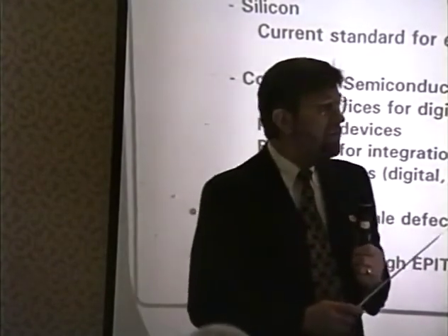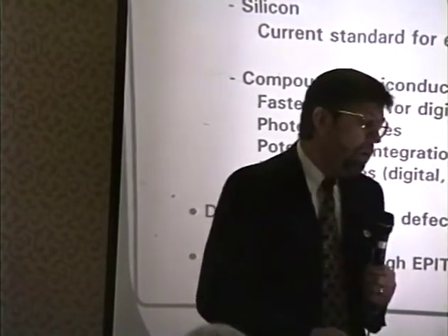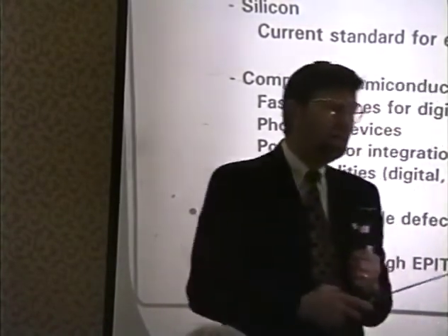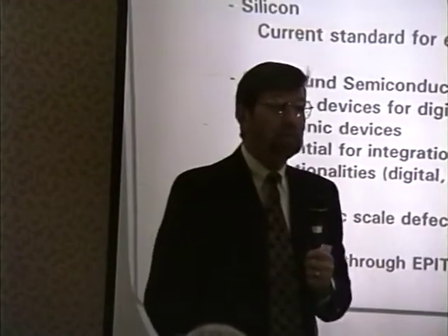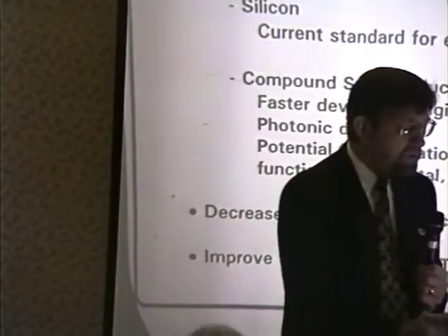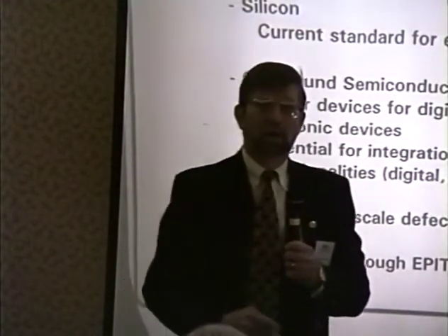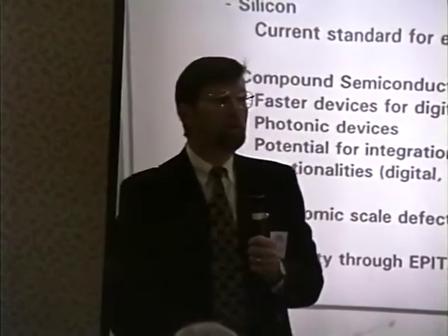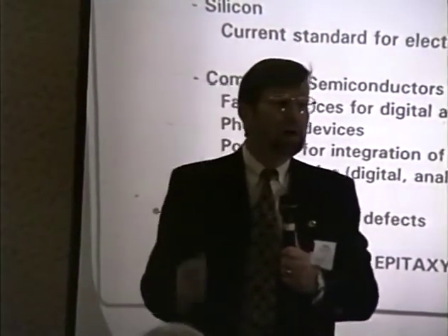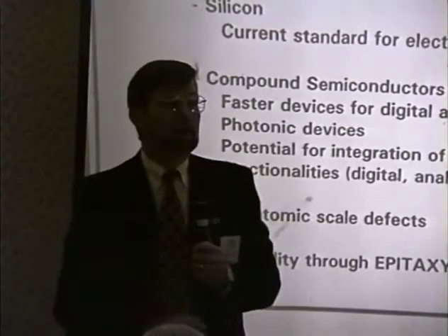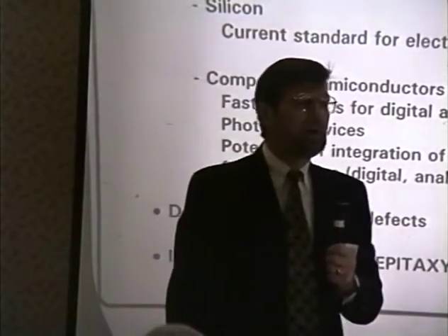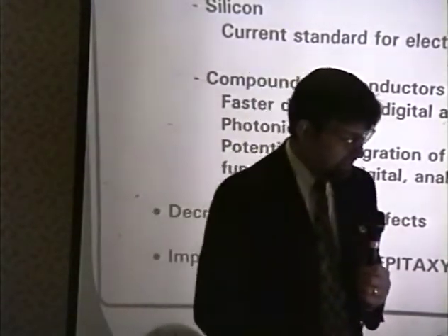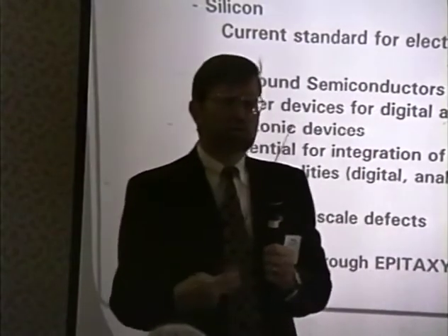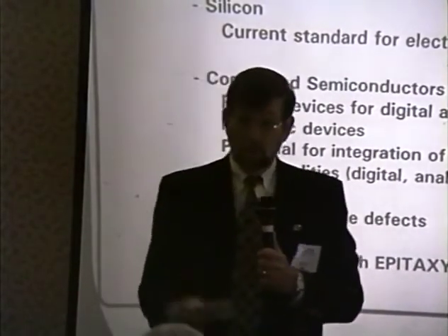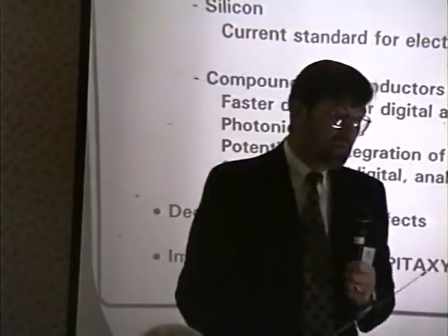Now, that's changed most recently, but there's still a lot to do. One of the problems for not using these unique materials and the high-performance materials is because they have too many atomic scale defects in them. They are not like silicon. You simply can't grow a single crystal boule in your garage and have 10 to the 8th defects per cubic centimeter. You have 10 to the 16th, 10 to the 15th defects per cubic centimeter. Millions of times larger number of defects, and you've got to reduce those defects to make these materials usable and therefore realize their full performance.